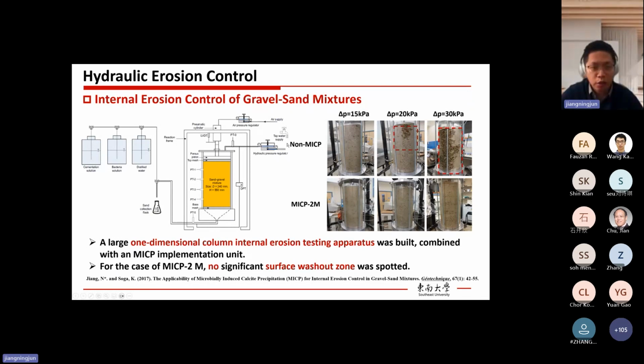In addition, we also installed a hydraulic pressure unit so we can achieve different hydraulic pressure levels. And also this sample is controlled by a pneumatic cylinder so that we can achieve different vertical stress levels. Then in this test, we test both untreated soils as well as MICP treated soils under different hydraulic pressures. So this graph is quite obvious.